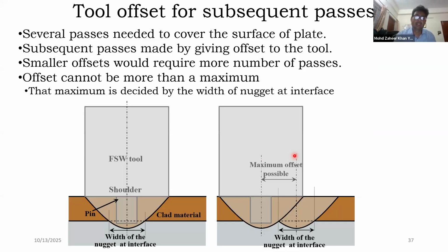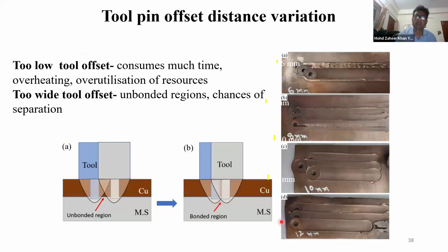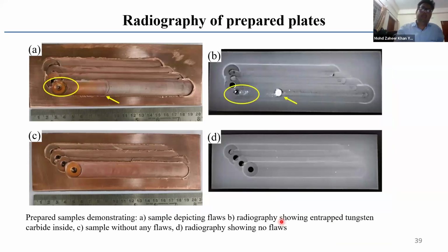Then the other part was how to select the offset distance. So this schematic will help you. If we are performing friction stir welding, then this parabolic zone of stir is created, and this stir zone is known as the weld nugget, and the width of the weld nugget at the interface of the clad is demonstrated by this arrow. So the maximum offset that we can give is equal to this distance. If any more offset is given, then there will be an unbonded portion remaining. Similarly, several trials were carried out, and it was found that an offset distance of 8 mm was sufficient. If more than 8 mm was given, then there were unbonded regions, and if a very small offset was given, then unnecessarily a lot of welding passes had to be carried out. So this is the radiograph of the clad plate that has been produced.